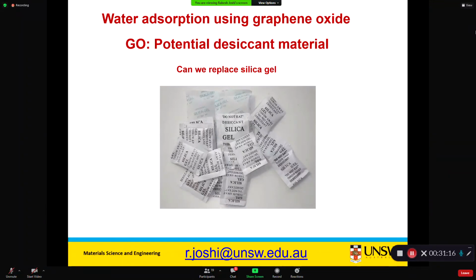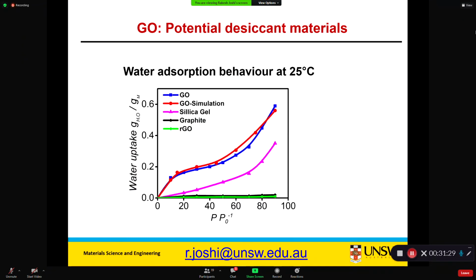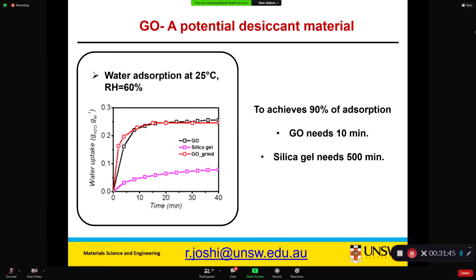Okay, the other application was because we know that graphene oxide absorbs water at a very high rate. It loves water, so we thought, can we replace silica gel, which is a commercial benchmark for water absorption? We did some work. You see, this is graphene oxide and this is silica gel. Graphene oxide is completely outperforming silica gel at 25 degrees for water absorption, and it achieves 90% of absorption in 10 minutes, while silica gel needs 500 minutes.